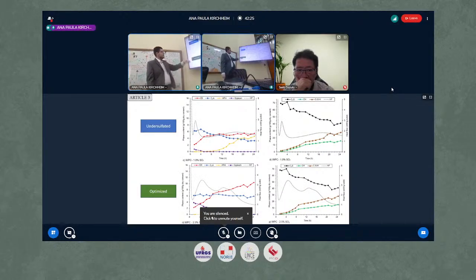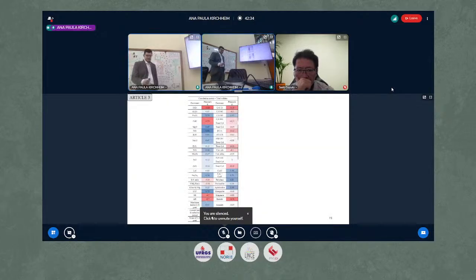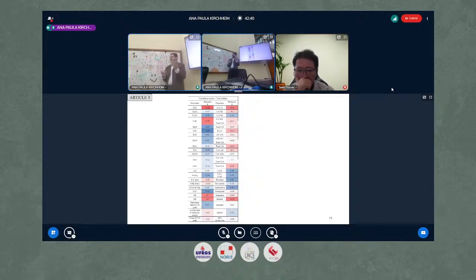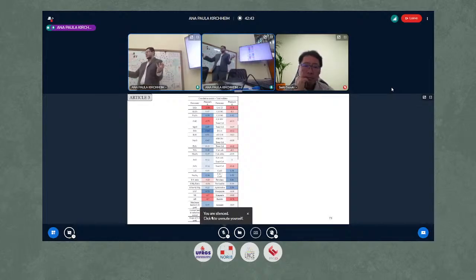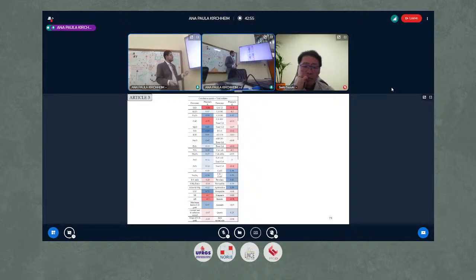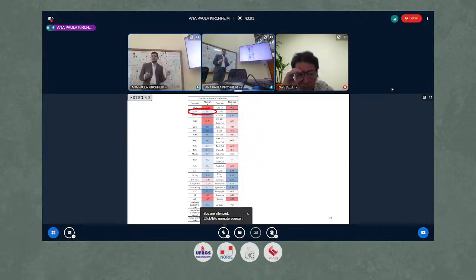We also see here in terms of white cement clinker with 1 and 2.5% of sulfate. So, what explains the different optimum sulfates from the clinkers, varying from 2.5 up to 4.3%? We tried to analyze Pearson's correlation with every parameter that we could find, so chemical, physical and mineralogical. And we don't see good correlation, for instance, from the alumina content in clinker, or from the C3A content in clinker, or the C3S content in clinker.